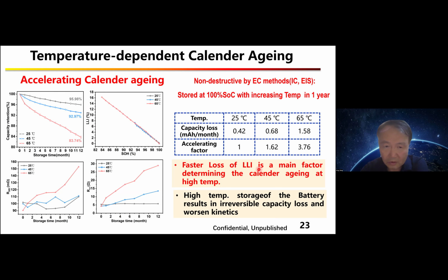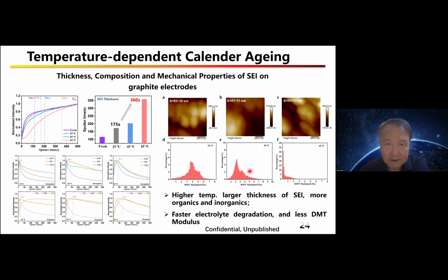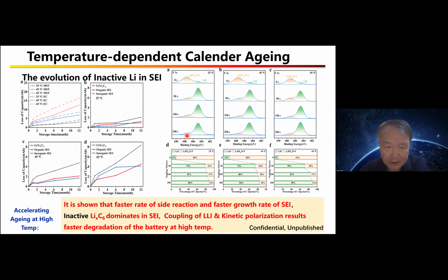So for this kind of calendar ageing, we also check the thickness, composition, and mechanical properties of the SEI on the graphite. We found that at high temperature, there is larger thickness of the SEI and also more organics and inorganics. I think due to the high temperature, faster degradation of the electrolytes, possibly the salts, also causes stiffer behavior of the SEI.